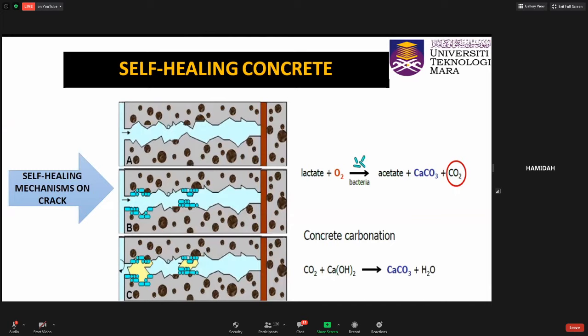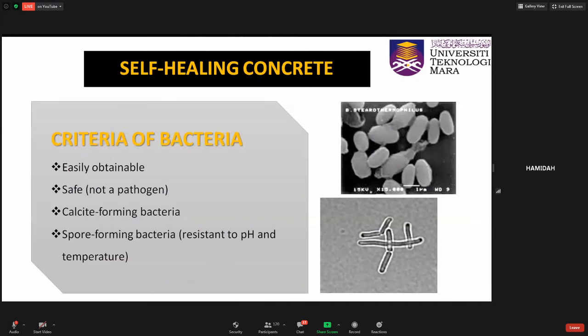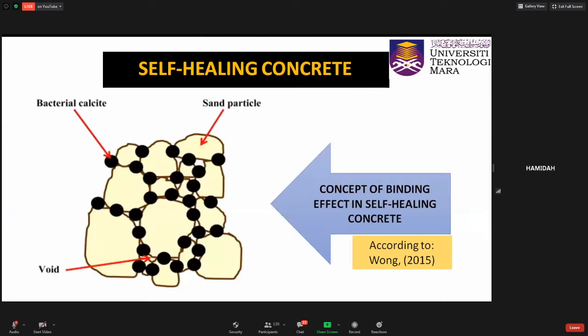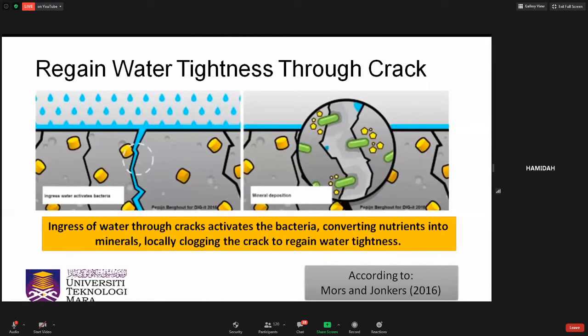Bacteria used for self-healing must be easily obtained, safe, calcite forming and spore forming bacteria which are also resistant to pH and temperature. The calcite formed from bacteria will fill up the voids in between the aggregates. This is the illustration that can be made when the calcite is formed in concrete. Ingress of water through cracks activates the bacteria, converting nutrients into minerals, locally clogging the crack to regain water tightness.